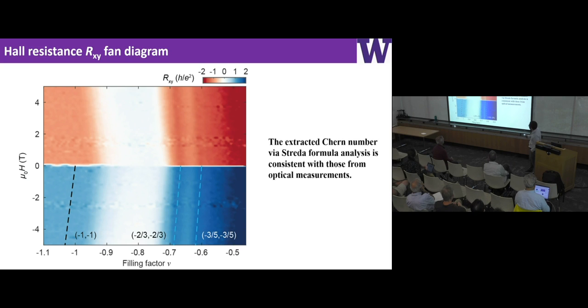And when you flip the sign of the magnetic field, the sign of the slope also flips. This basically tells you it's not a quantum Hall state. Actually, it's a quantum anomalous Hall state. So the take-home message of this data is that it is consistent with our optical measurements. Basically, it's the same measurement, just using different probes.